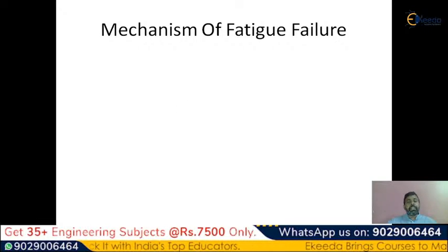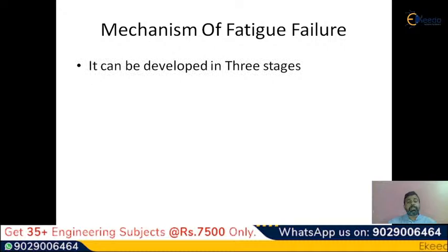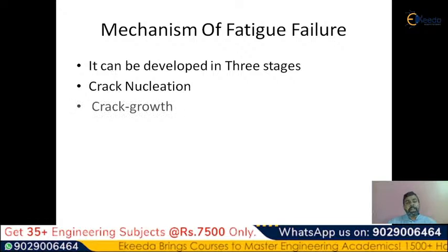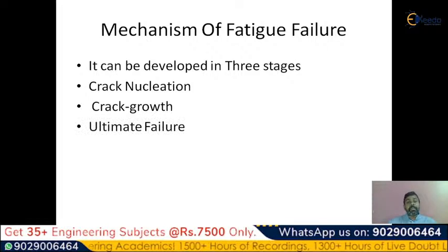Now let me discuss the various stages in the mechanism stage-wise. First of all, the crack nucleation, that means the crack is going to start in the material. After that the crack is going to grow. This is the second stage of the fatigue failure. The third stage is ultimate failure. Please observe the three words here: crack nucleation, crack growth, ultimate failure. These are the three different stages of the failure mechanism in the material.